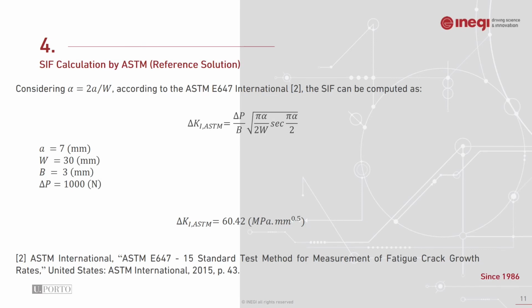And finally, the SIF calculation by ASTM, which is considered as a reference solution. Alpha is 2a over W, according to the ASTM E647 International, as can be seen on the bottom side. So the stress intensity factor was calculated as 60.42.